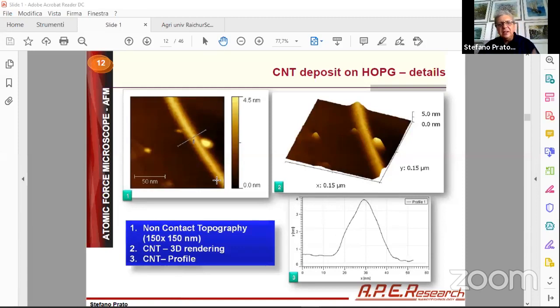So this is a single wall carbon nanotube. This is an example of very nice resolution. As I said, the first argument we're talking about will be resolution. So resolution is, first of all, lateral resolution. This image is 150 by 150 nanometers, so it is very, very small. This is the X and Y resolution, but another parameter is the Z resolution. Z resolution is when you do a cross section, what is the smallest size that you can measure.